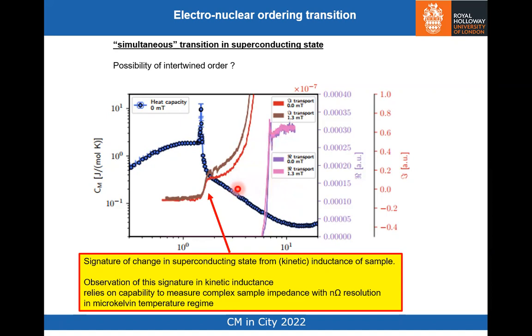But because of the way that we do the transport measurements, we measure the real and the imaginary parts of the conductivity. So we're sensitive to, for example, the kinetic inductance of the sample, and that shows a small signature here. The signature is tiny, some tens of nanoohms, but we can detect it. What this indicates is a change in the superconducting state above and below the transport signature. These measurements are done on 2 different cryostats, but the temperature scales are extremely well aligned because they're based on noise thermometry.